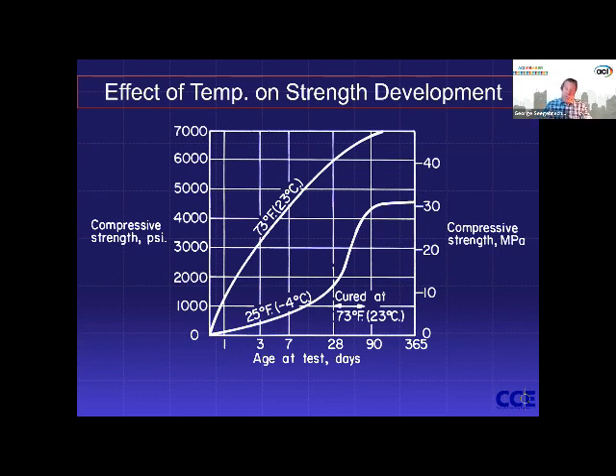And long story short, they sent a couple cores. We subjected them to accelerated curing, so higher temperatures, in order to kind of send a canary to the coal mine saying, is it still salvageable? And we said, if you put the protection back and heat the area, you should be fine. And they were 2 weeks ahead of schedule anyway, but they wanted to know pretty quickly. So that's why we had to accelerate the curing, that if they wanted to just rip it out and redo it, they could just get back on normal schedule.